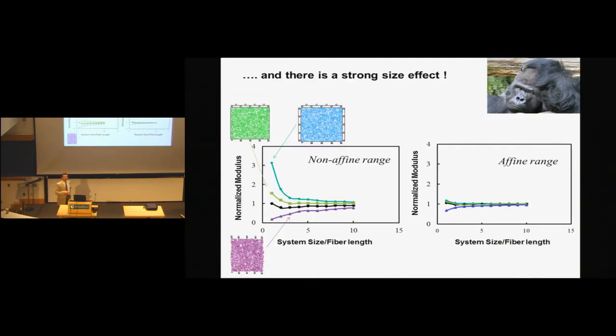Another headache, strong size effects. The moduli I'm computing are very much dependent on the boundary conditions and the size of the patch I'm considering. So if I want to compute moduli which are size independent, I have to use really, really large models. This shows an example of the modulus of the network computed for various model sizes. This is the model size, the size of this box divided by the fiber length. And you see that for small models, we get a very strong size effect. And we have to have models or domains which are as large as maybe 20 fiber lengths to make sure that we are in the convergence domain.